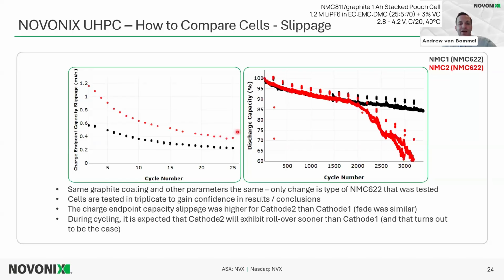So the main use of this slippage metric is to compare one cell to another, and this is exactly showing that. And when you do a lot of this kind of testing and you do similar cells, you can have a much larger comparison. So if you had 10 cells and then your new cell, or the new cathode material within that cell, had lower slippage, you can be really excited early on, because the prediction would be that you'd have that rollover much later on. So that's a way to compare one to the other.